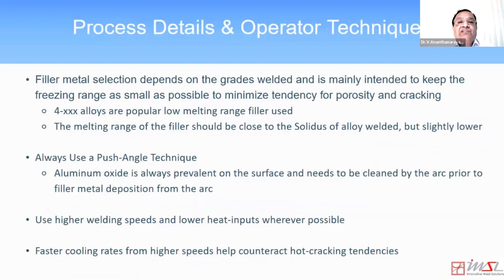Filler metal selection depends on the grades welded and is mainly intended to provide a low freezing range filler that melts at low temperatures, such as silicon-rich fillers, which are 4000 series alloys. And the melting range of the filler should be close to the solidus of the alloy welded.